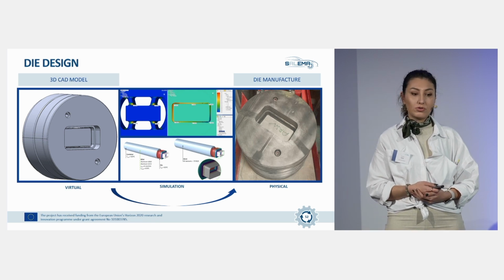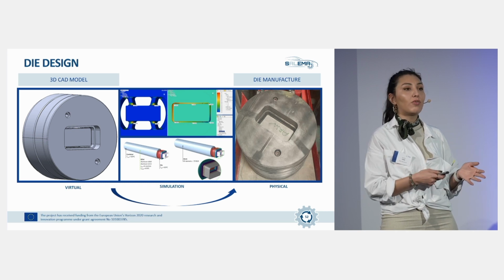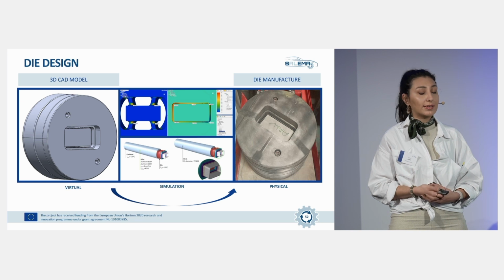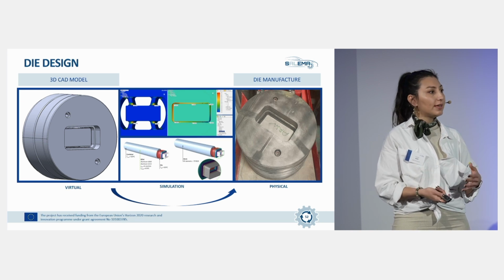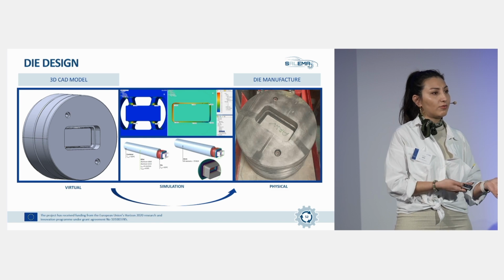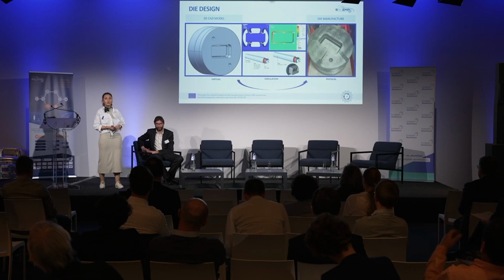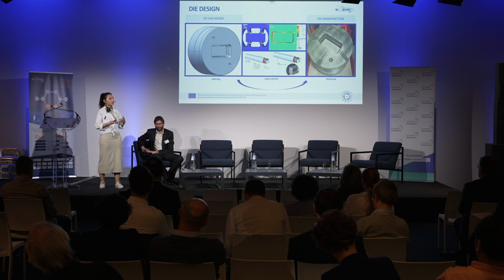In order to carry out the extrusion, we have designed a 3D CAD model of the extrusion die first. After that, we have analyzed it with Q-form simulation carried out by ASAŞ, and we have revised the extrusion die a couple of times with respect to the results of the Q-form simulation. The extrusion die geometries were shared with our partner Eurecat, and they made the simulations with Altair Inspire Extrude software. They have come up with the related extrusion parameters like temperature, ramp speed, and we have also gotten these values from the lab scale trials too. And we have produced the die to be able to continue with the extrusion process.